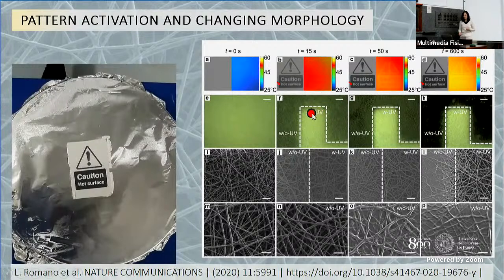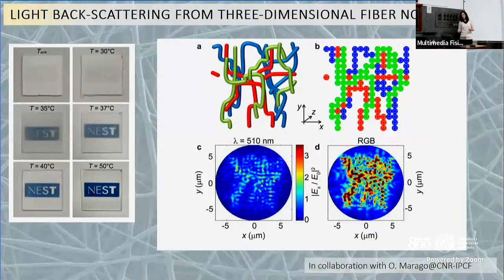So what's going on around? Let's first say that the H is a part where UV light entered the material, okay? So it was exposed to UV. And the second interesting part is that if you follow here, you see that the part that was not exposed at a certain point disappeared in the form of fibers. So the fibers from the bottom of the surface start melting together. And when they melt, they totally change their appearance, so they change their transmission properties. This behavior can be rationalized by the T-matrix formalism.